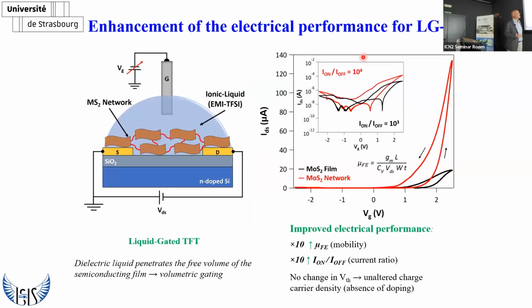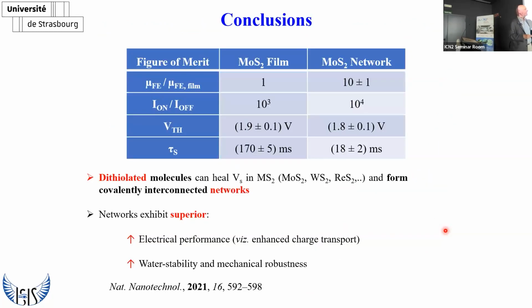And then we were interested to see if we can improve the electrical characteristics of the device. And we use again the liquid-gated TFT, because having the dielectric liquid that penetrates into the free volume, we have a volumetric gating effect. And to make the long story short, upon network formation, we have an increase in the field effect mobility of 10-fold, an increase of the on-off ratio in the transistor of 10-fold, and no change of the threshold voltage. Therefore, we have an absence of doping. We also have the device switches much faster, by 1 order of magnitude.